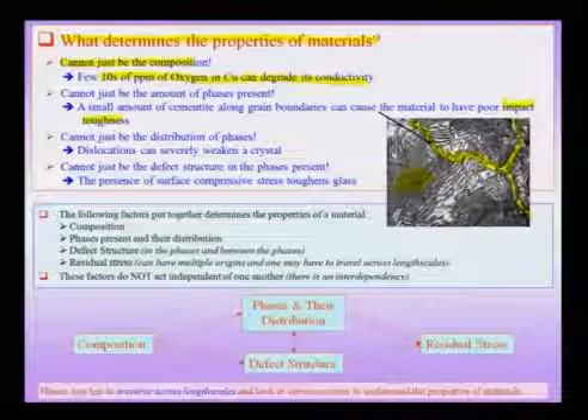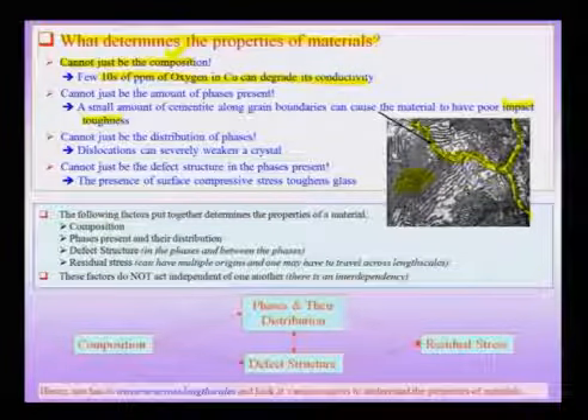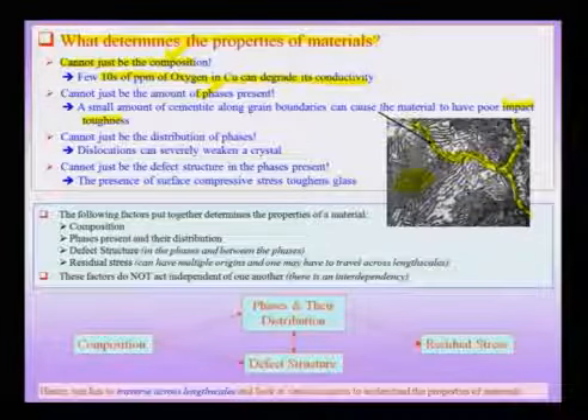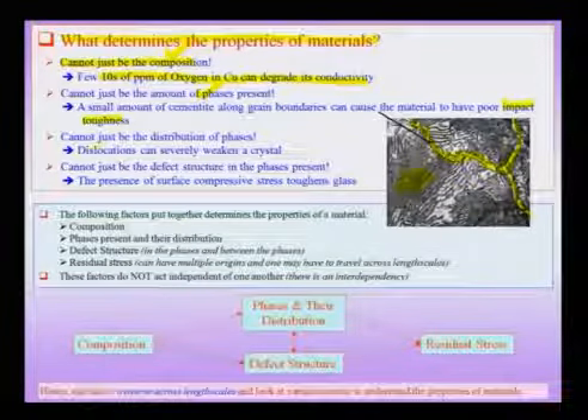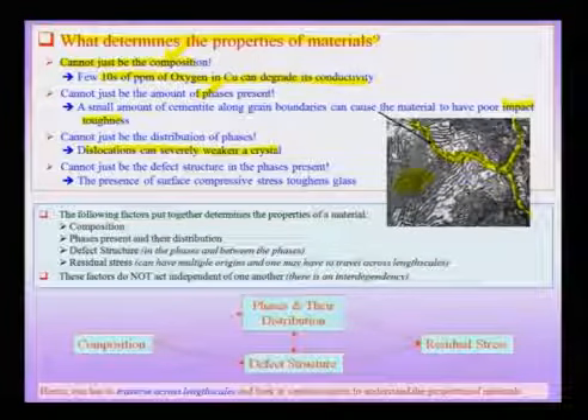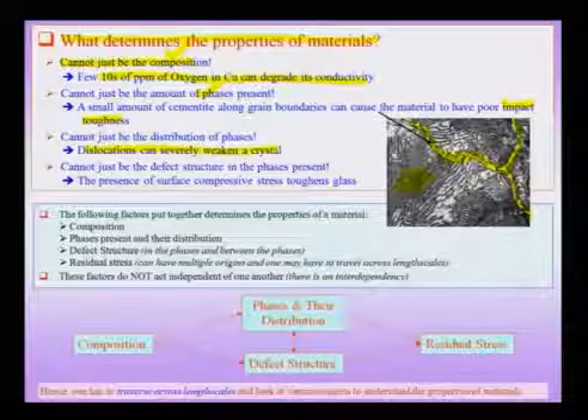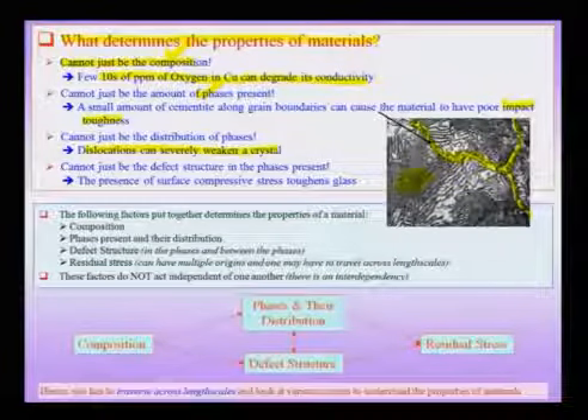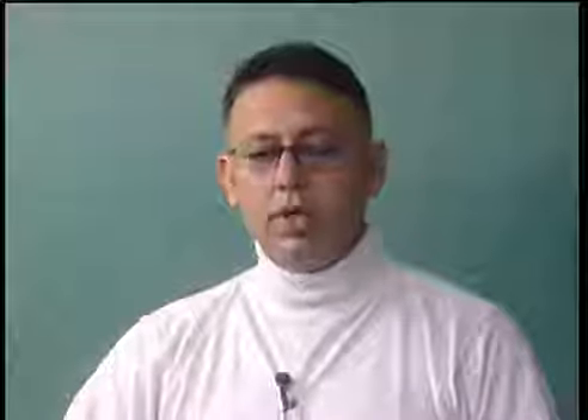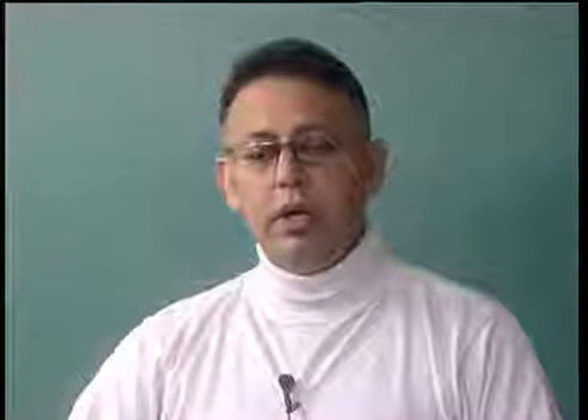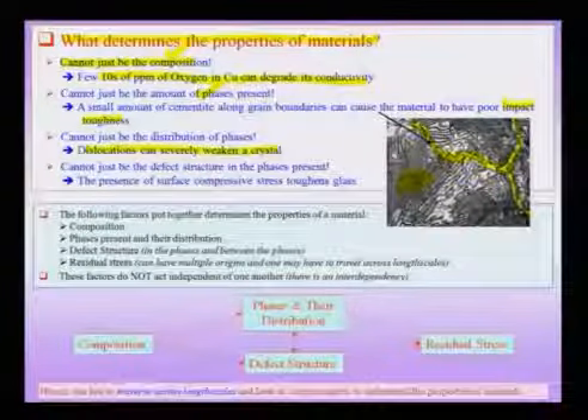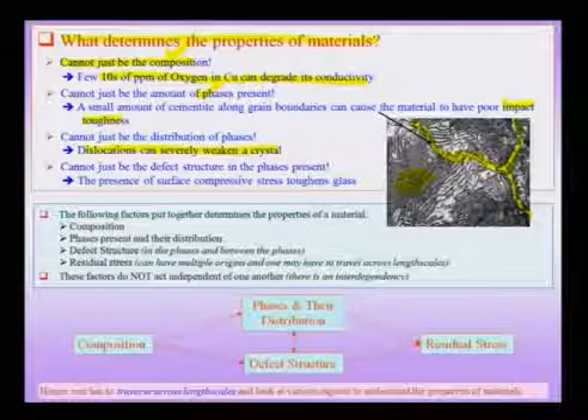In other words, I need to worry about the composition, number 1. I need to worry about the phases present, number 2, but that is not enough. For example, if I have dislocations in a phase, this can weaken a crystal severely. Suppose I take an absolutely pure, defect free single crystal and try to measure its shear strength. It will turn out to be of the order of gigapascals. But in the presence of dislocations, which are crystallographic defects, the strength of the material can fall by a few orders of magnitude and can severely weaken the crystal. This implies that I need to know the defects present in the material, apart from knowing the phases and their distribution.